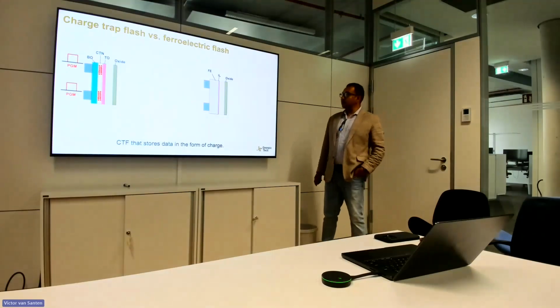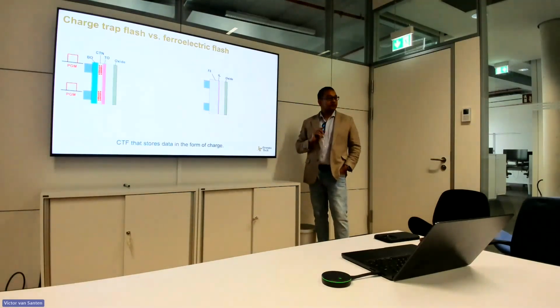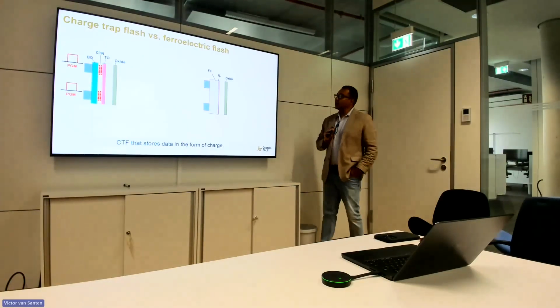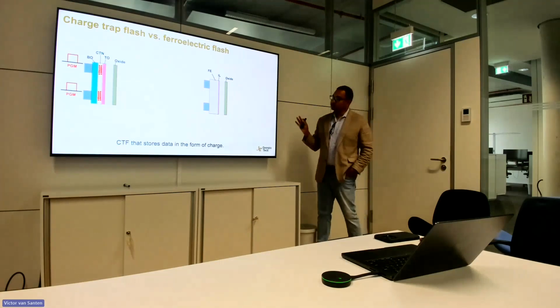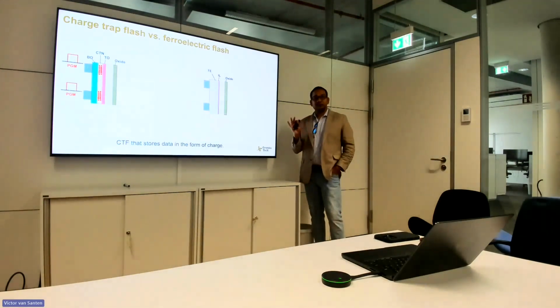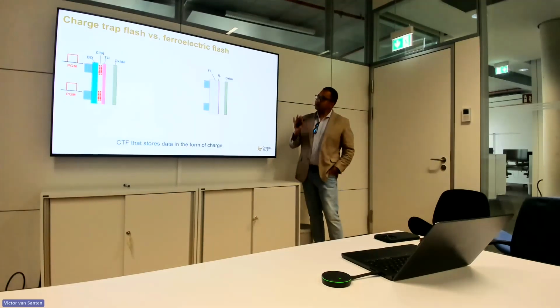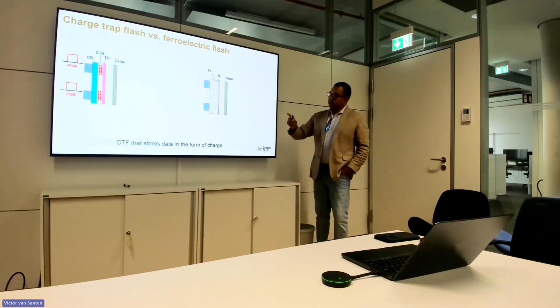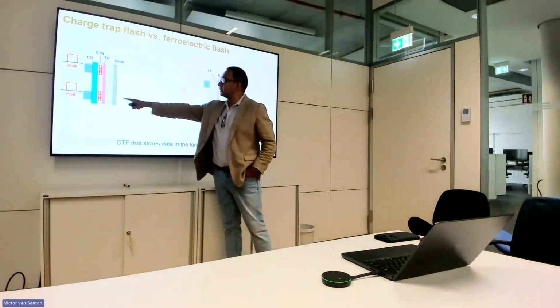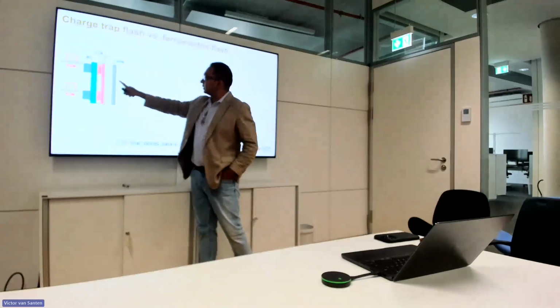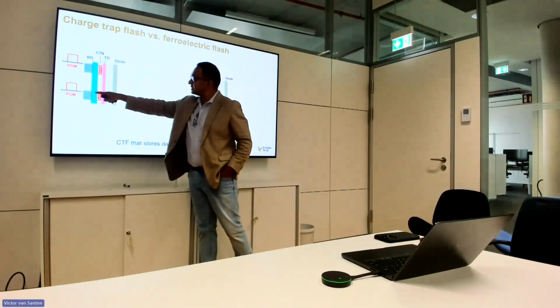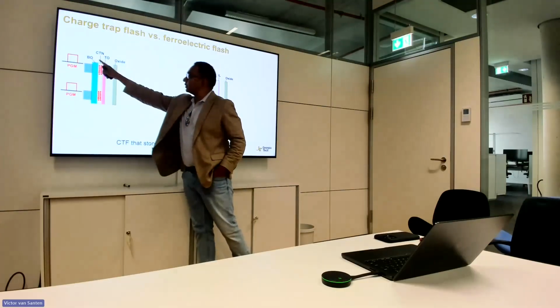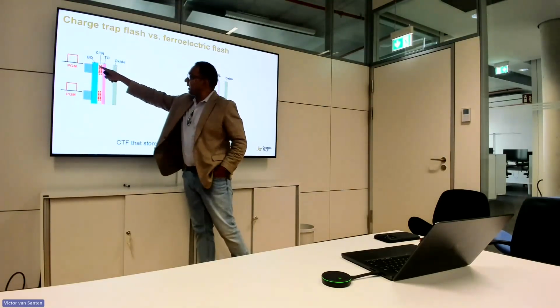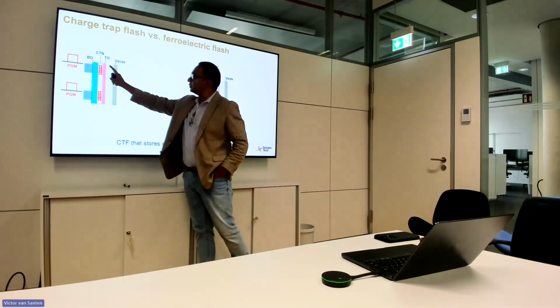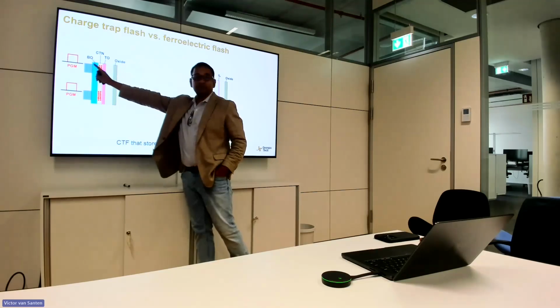Okay. So I'll now explain how we think about a ferroelectric field effect transistor for NAND flash applications. I will use a slightly different kind of schematic diagram from what we usually use to explain a ferroelectric field effect transistor, because I really want to make a comparison between standard charge trap flash and a ferroelectric flash. Okay, so on the left, we have a vertical NAND flash structure. This white region is the channel. This is the gate stack. The NAND flash has a gate stack of a bottom oxide, top oxide, and a charge trap nitride layer. And if there are electrons trapped here, then we store some data, 0 or 1, and that happens when we apply program pulses.